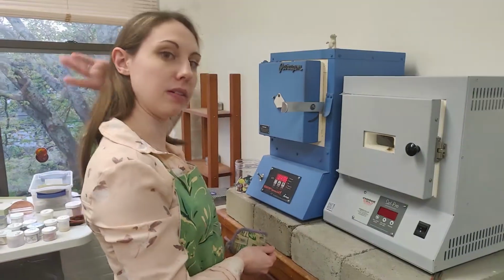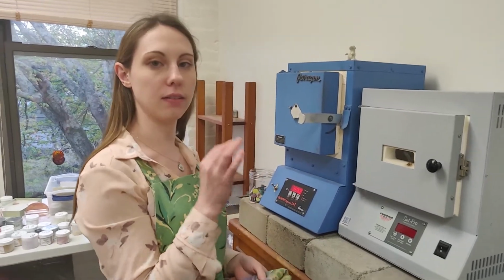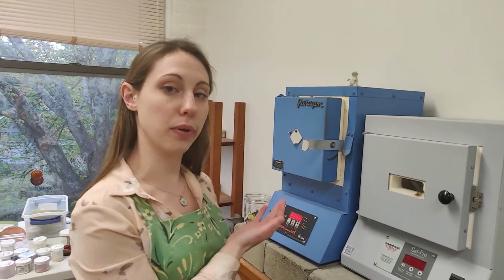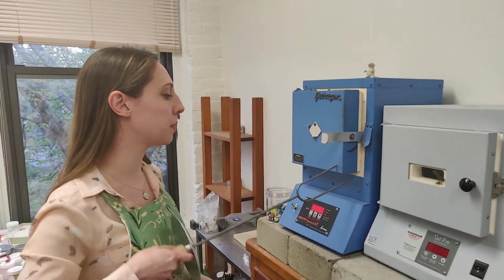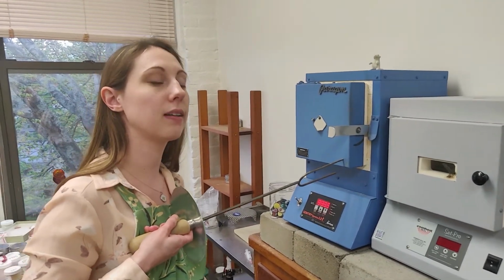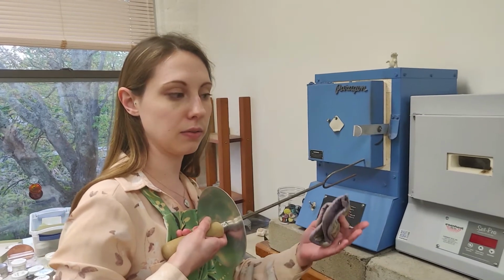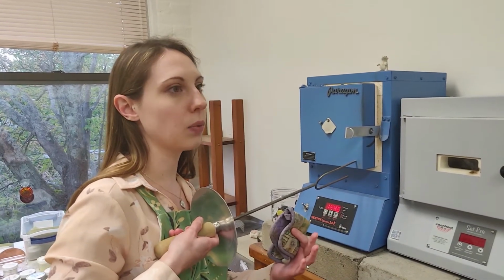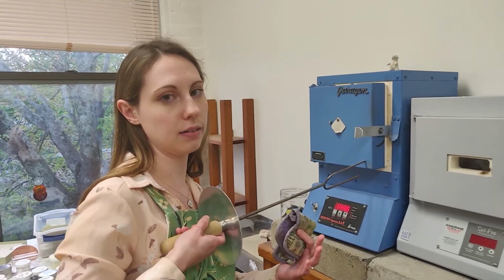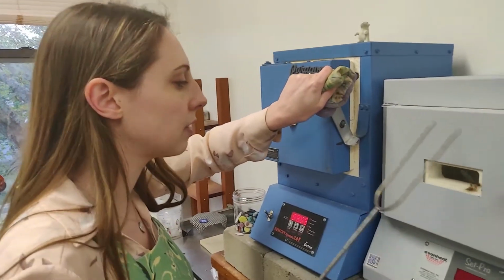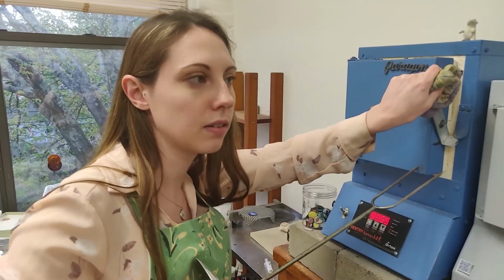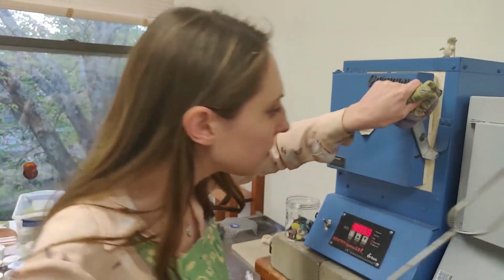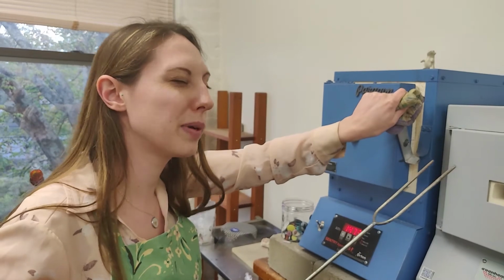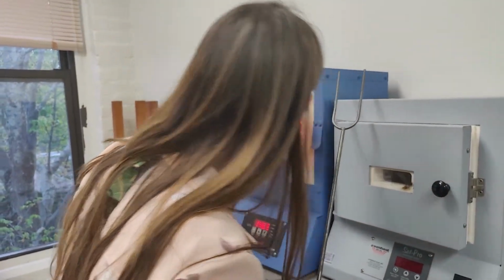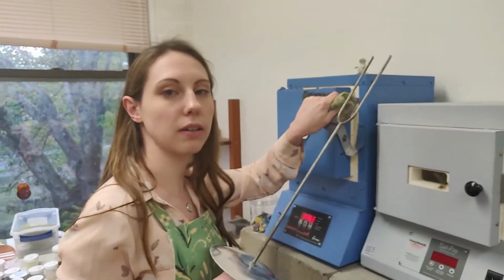Firing is the most temperamental because when the graphite is on the surface, it starts to burn off in the kiln. So we want it to go up to temperature as fast as possible so that the glass turns molten, and the graphite, instead of burning off too quickly, will sink into the molten glass and be preserved in the glass. And it's starting to get molten, but I just like to give it a few more seconds to sink. The longer I leave it, the better it sinks into the glass, but you don't want it to burn off either. So that seems maybe another couple seconds.